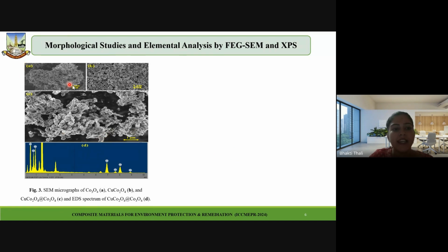So figure 3A indicates the SEM micrograph of cobalt oxide. As we can see, irregular shaped morphology is seen for cobalt oxide nanoparticles, which is consistent with the literature. For the copper cobaltite particles, spherical morphology is seen.